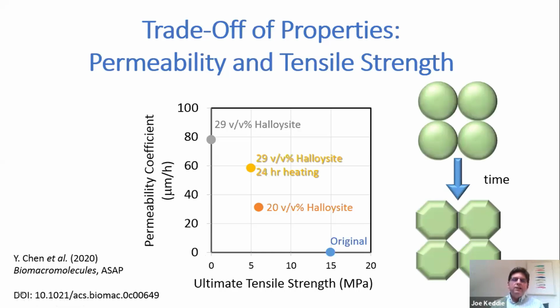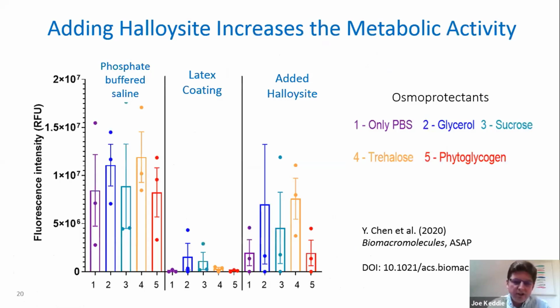And by increasing the film formation time, we were able to drive the particle deformation a bit further and encourage some of this interdiffusion, which is so important to get the strength and the cohesion in the coating. So how did this all work?